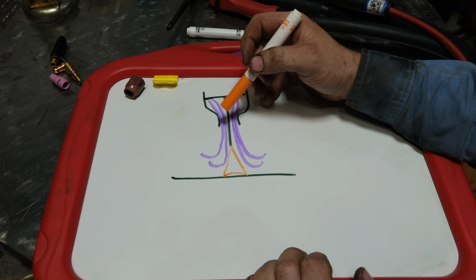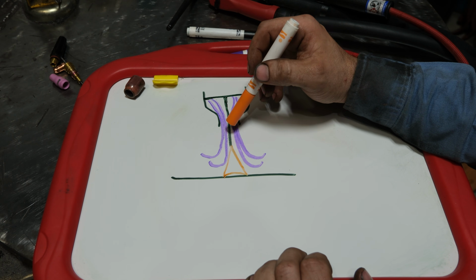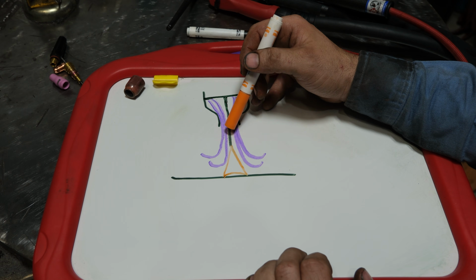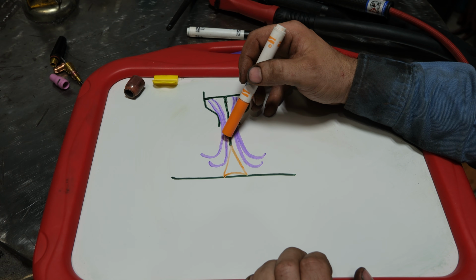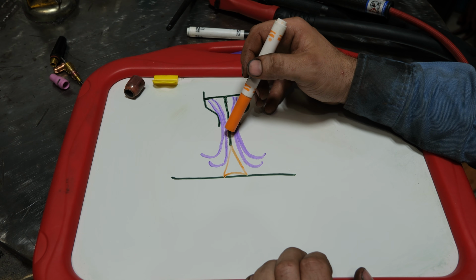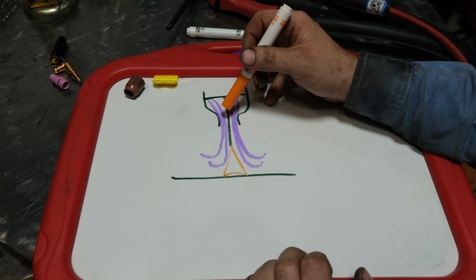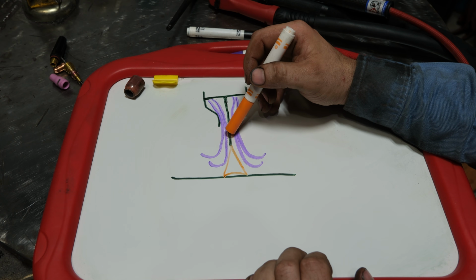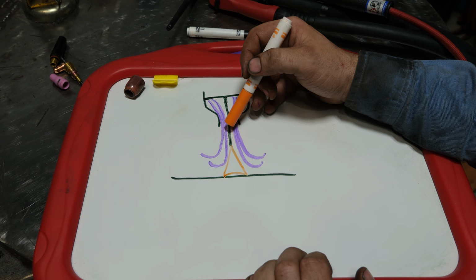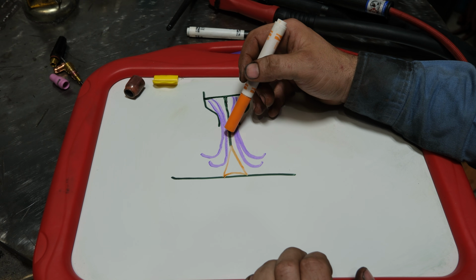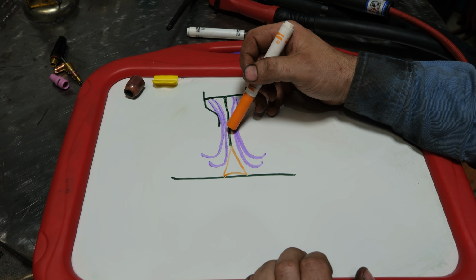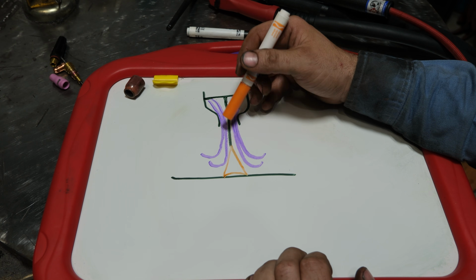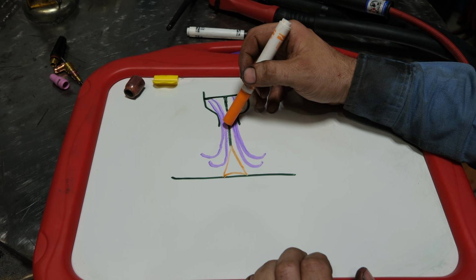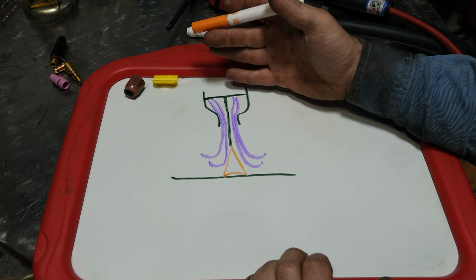And that's very important because tungsten will only handle high temperatures when it is not exposed to oxygen. So that flow of argon will protect that tungsten and allow it to glow red hot, white hot even, without melting. If you were to remove the shielding gas, what would end up happening is the oxygen in the air that you breathe would react with that red hot tungsten, and it would be consumed. It would basically burn up much like a sparkler in a very short time, like a second or two. Anyone who has run out of shielding gas or forgot to turn it on can attest to that, would definitely know what happens then.